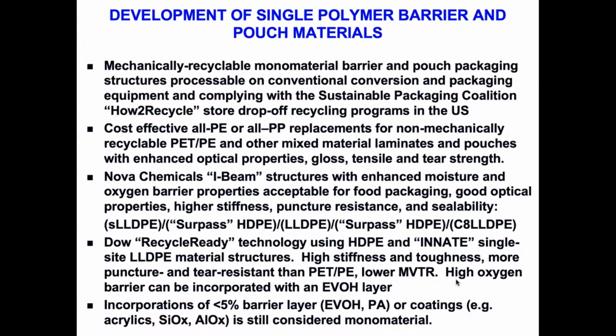This was started off essentially by two companies, Nova Chemicals with their I-beam structures. And there's an example of the kind of structure that Nova Chemicals came out with: enhanced barrier properties, acceptable for food packaging, good optics, high stiffness, puncture resistance, sealability. The other company is Dow Chemical with its recycle ready technology using HDPE and single site linear low density polyethylene. Again, very good physical properties, good barrier properties, and if very high oxygen barrier is required, an EVOH layer can be incorporated, and it's considered that the incorporation of less than 5% by weight barrier or coatings is still considered a monomaterial.